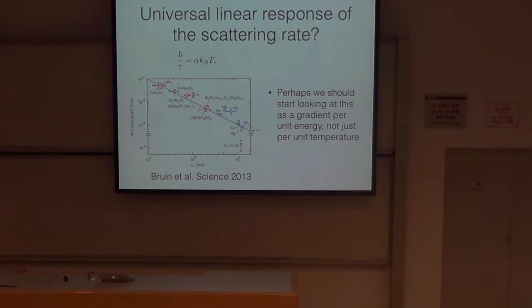Okay, which brings me back to one of my earlier slides, which was Andy Mackenzie's suggestion that maybe there's some kind of universal scattering rate for temperature, or maybe what we're seeing for materials near quantum critical points, if that is indeed what's going on, is that actually it's a universal scattering rate per unit energy. And then you just need to convert the right variables to energy rather than just looking at them individually as a function of temperature alone. You'll see very similar relations, for example, if you looked at scattering rates versus omega. It's what photoemission people do and people in optical conductivity do, that you'll see that a lot of relations like T squared plus omega squared will come up. But here we just have a T squared plus b squared.